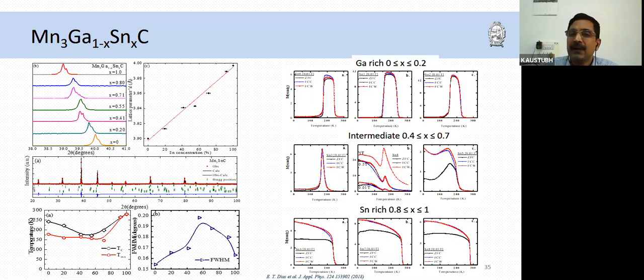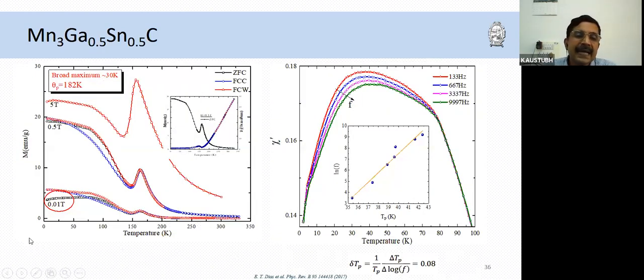We looked at magnetization, and here also we could divide straight away into three categories. These are the gallium-rich alloys, which show a behavior similar to Mn3GaC. These are the tin-rich alloys, which show behavior similar to Mn3SnC. But then there are the intermediate alloys, which show very different behavior. And we tried to look at one of them in greater detail, that is the central composition, gallium 0.5, tin 0.5. So this is the Ga0.5Sn0.5 magnetization data.